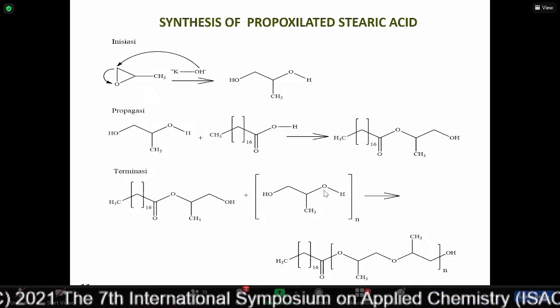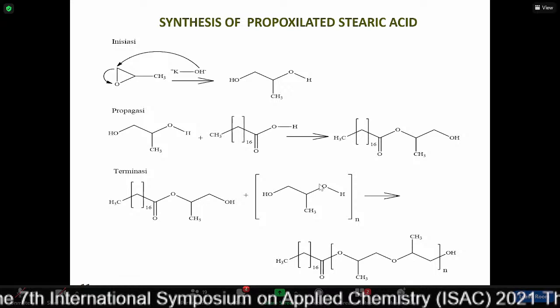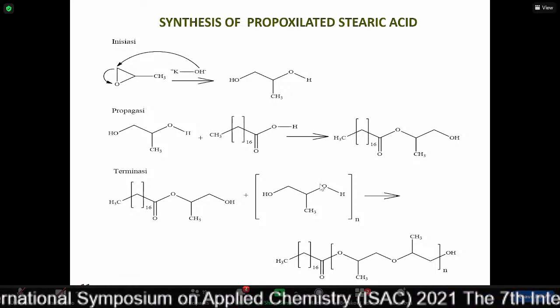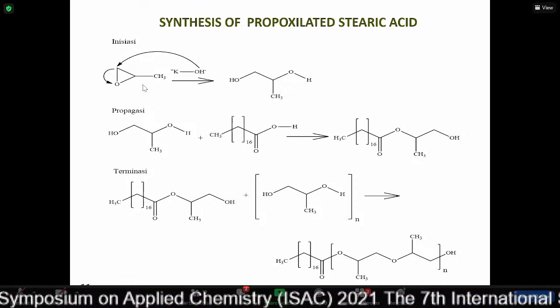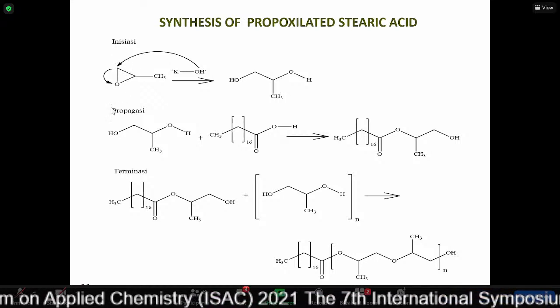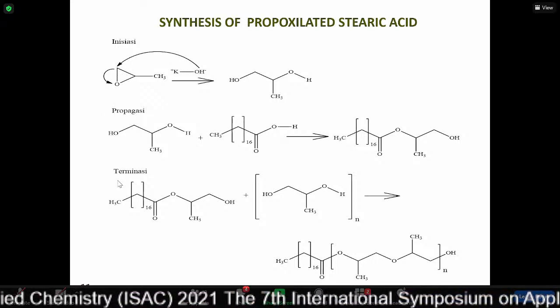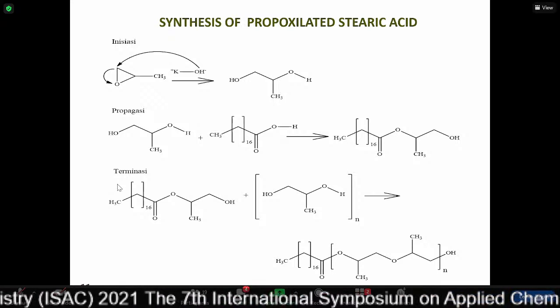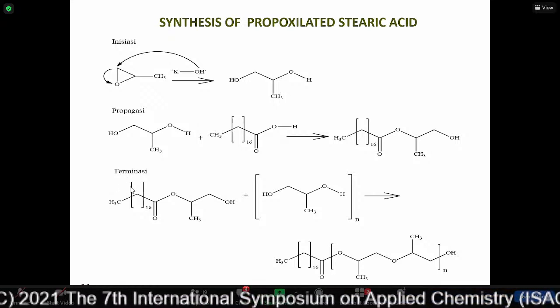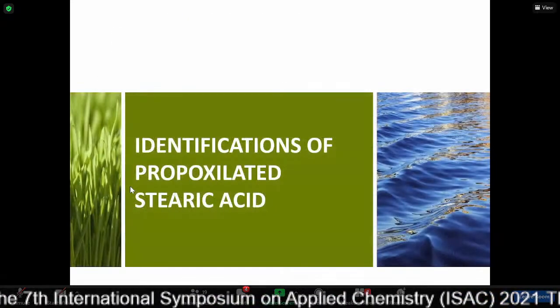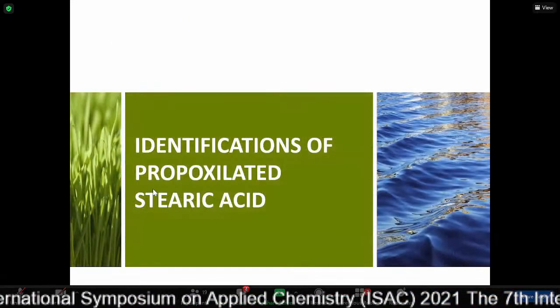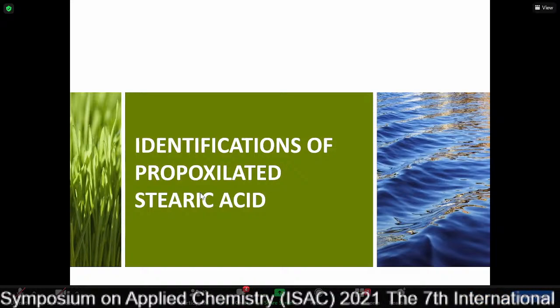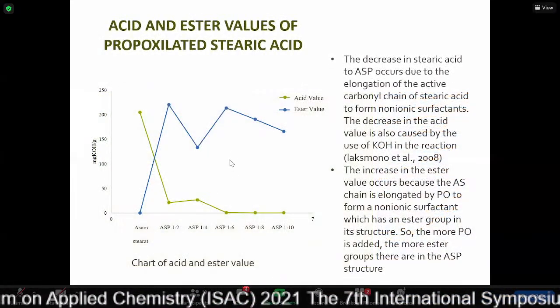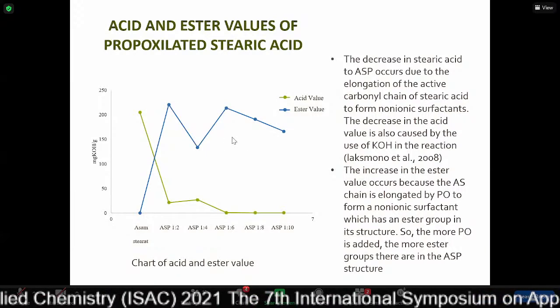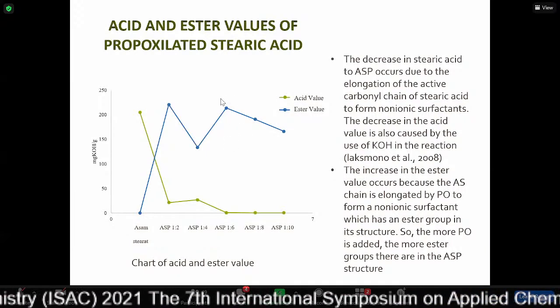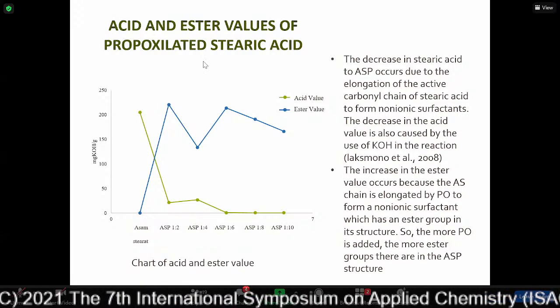Stearic acid propoxylation surfactant can be synthesized through 3 steps. The first step is initiation, continuing with propagation, and the last step is the termination of the reaction. And this is for identification of propoxylated stearic acid. So this is the acid value and ester value of the propoxylated stearic acid.